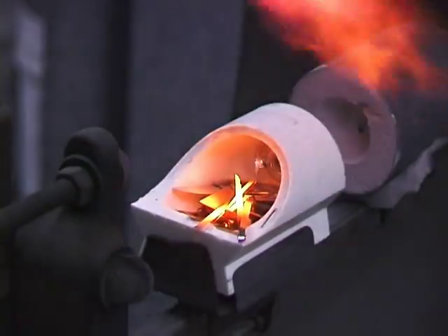We have a situation where a lot of people have negative feelings about cobalt — I personally don't understand it, but they do. We're trying to get past that barrier, but if it's new and they don't like it, they won't change. While platinum cobalt is the finest casting alloy — if you want fine detail, there's none better — it's having a hard time in the field because it oxidizes a little bit, it's magnetic a little bit, and people don't like that. But platinum ruthenium, if you get past the learning curve and can repeatedly cast it without porosity, you've got one of the finest alloys in the world.